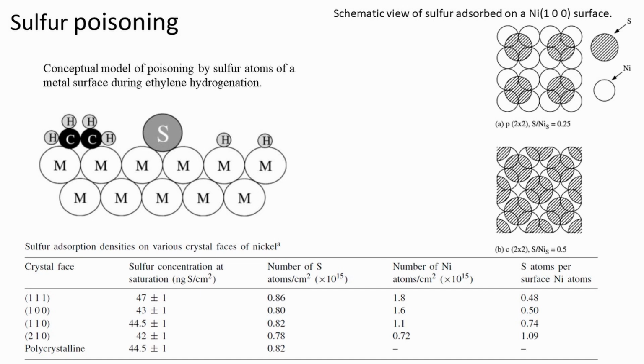Interesting facts. There are a number of industrial processes in which one intentionally poisons the catalyst in order to improve its selectivity. For example, platinum-containing naphtha-reforming catalysts are often presulfided to minimize unwanted cracking reactions. Sulfur and phosphorus are added to nickel catalysts to improve isomerization selectivity in the fats and oils hydrogenation industry, while sulfur and copper are added to nickel catalysts in steam reforming to minimize coking.